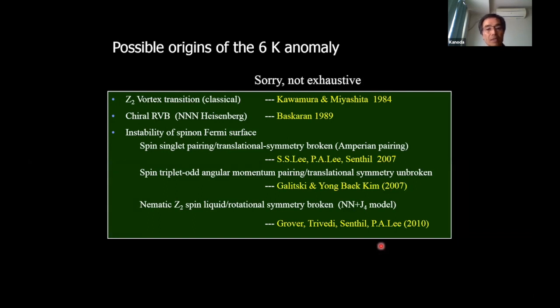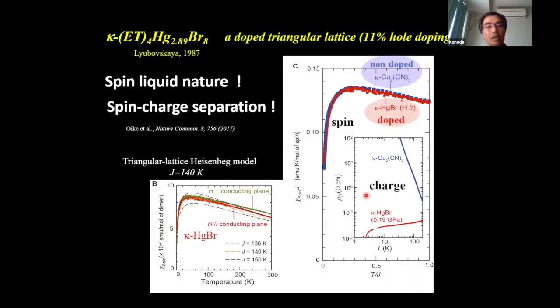Okay, this is a part of the list dealing with the theoretical spin instability. Next topic is the doped spin liquid. We have a doped triangular lattice. This material has non-stoichiometric compositions in the insulating anion layers. If the content of mercury is 3.00, in that case, this material is a Mott insulator. But this 11% missing content provides holes to the conducting layers. This provides additional holes, so hole doping.